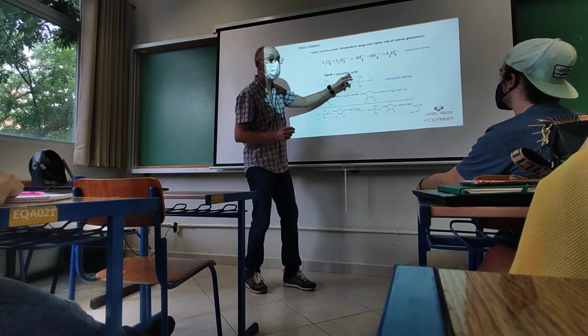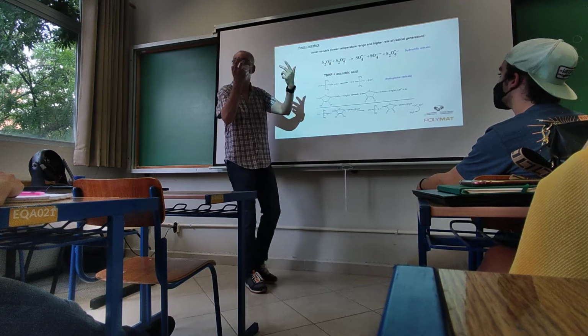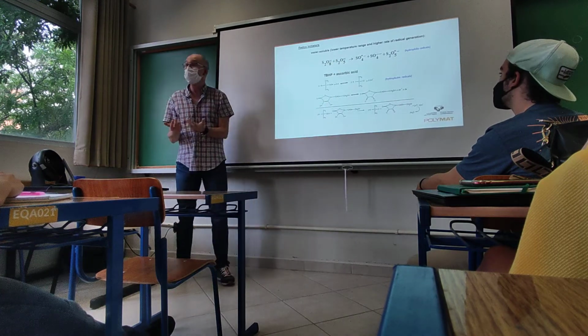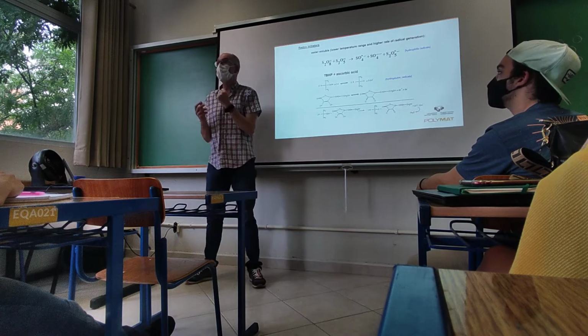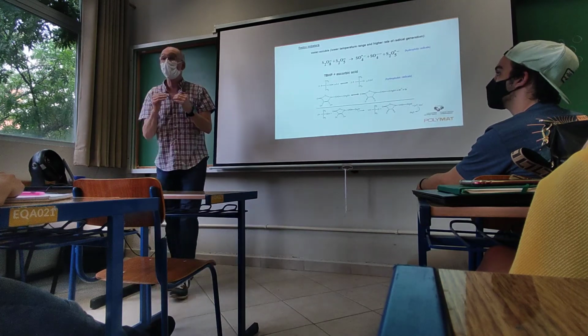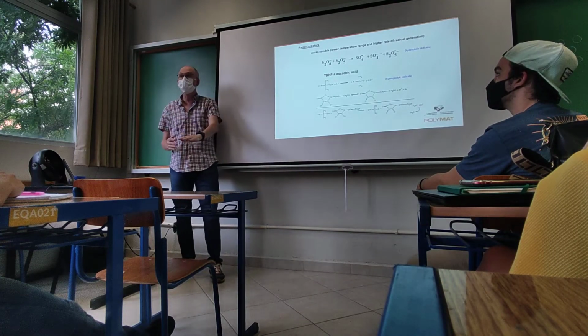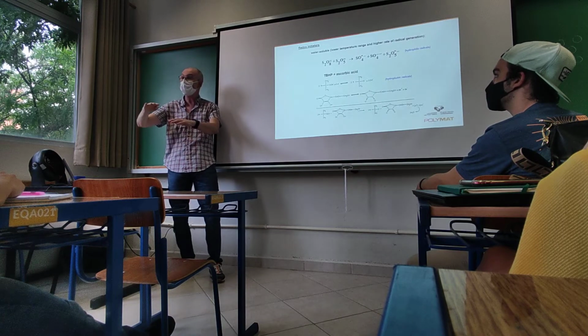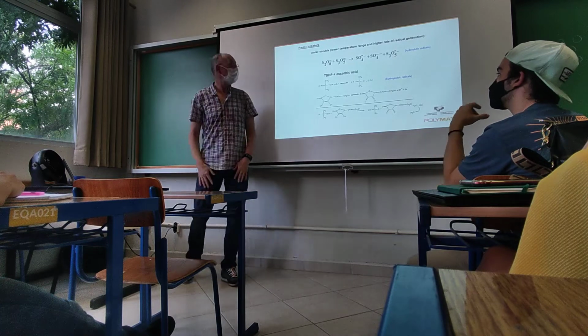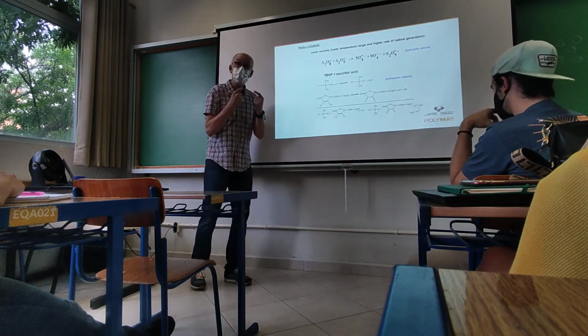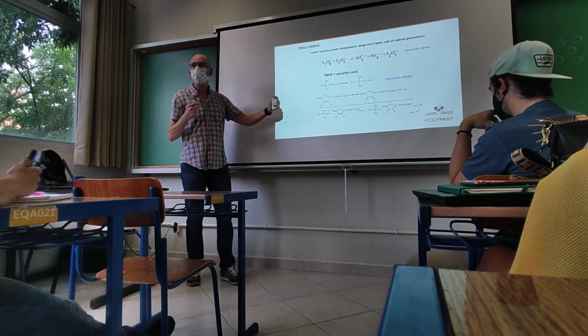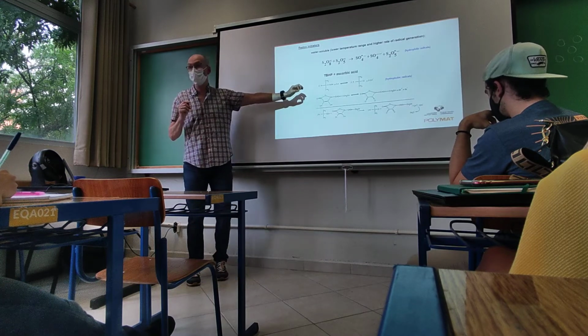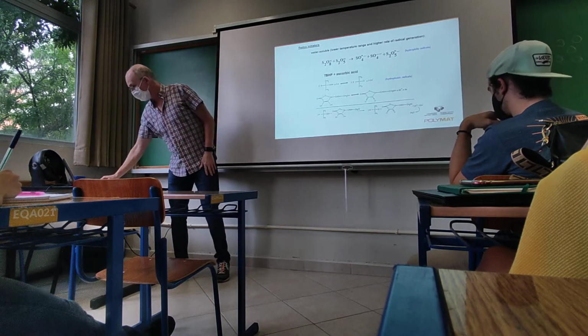The oxidant and the reductant, so the redox couple, can generate radicals. What is the advantage of the redox initiators? That you can generate radicals at lower temperatures. You don't need to go to 70 or 80 degrees. You can generate radicals at 40, 50 degrees. And in addition, the rate of generation of radicals is much faster with redox systems.